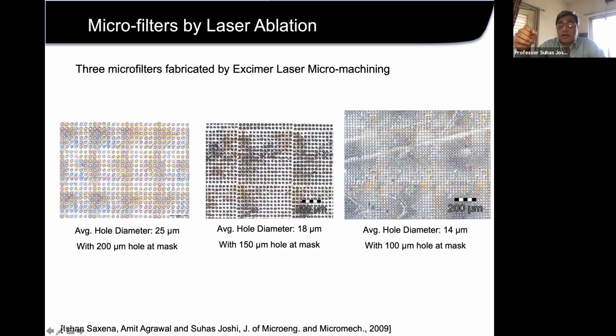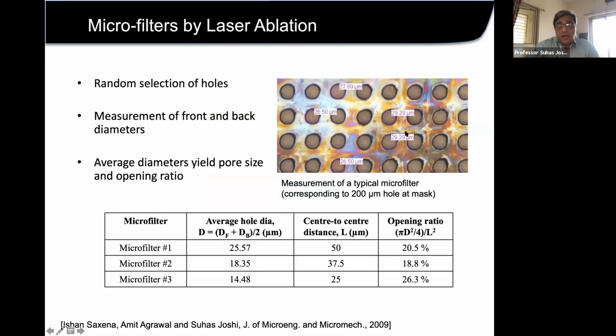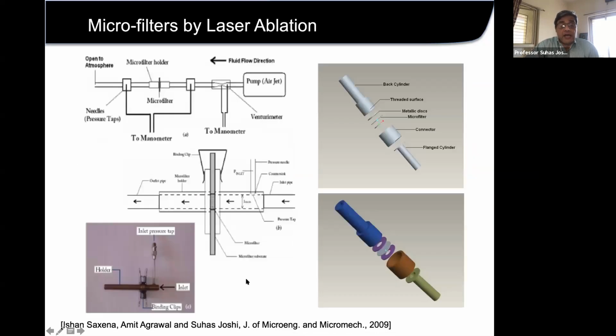A 14 micrometer hole is very small, and we could make it using a 100 micrometer mask because that reduction in the beams was possible. So you can see that even 25 micrometer holes are fairly small, fairly uniform in size. So these are the smallest holes we could make here. And then it can be put into a device, and you can measure the pressure drop across the microfilters.